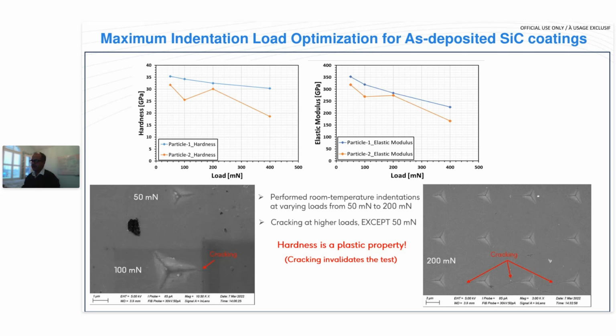And when we looked at the indents in the SEM, we saw cracking around the indents greater than 50 millinewtons. The 100 millinewton and 200 millinewton indents have very clear cracks around the edges of the indents. And hardness is a plastic property, so any cracking around your indents actually invalidates your experiment for the hardness measurement. The 50 millinewton indentations at room temperature were crack free. So we chose 50 millinewtons as the maximum load for these measurements.